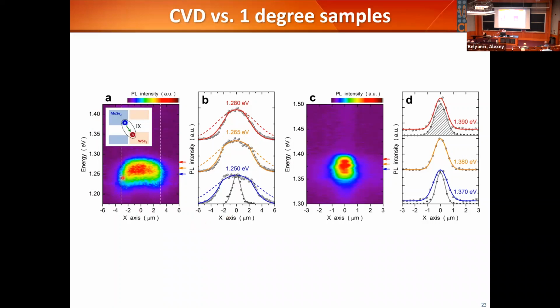The spatial extent: excitons move in the CVD because there's no Moiré potential. But when I have a small twist angle, they're localized. The spatial extent is still a couple of microns. That's because I cannot focus my optics better than that. So this is actually a diffraction-limited experiment.